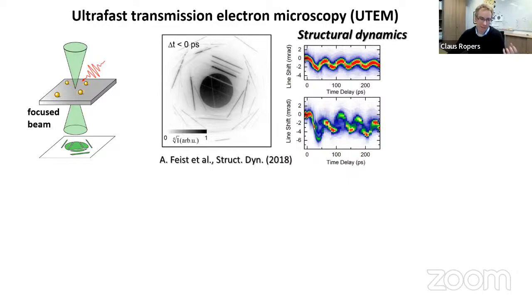And now the nice aspect of this with time resolution is that you can study the local structural evolution after optical excitation. So basically following these different lines, which correspond to different Bragg conditions in diffraction, allows you to study as a function of time and space, if you scan the beam, the local distortions of the unit cell, rotations, deformations, also volume changes, basically.